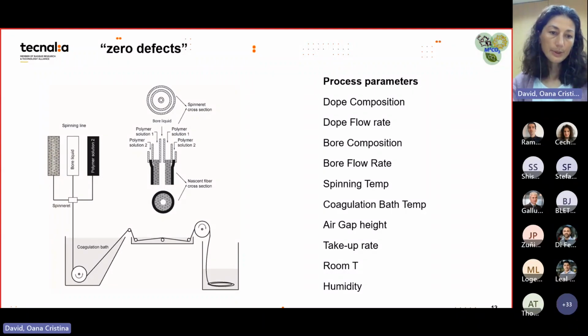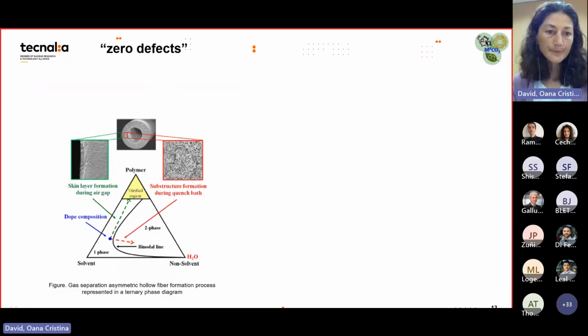So again, going back to the spinning device, as I said before, there are many process parameters we can change. The most important is the dope composition. Afterwards, when we actually do the process, we can change the dope flow rate, the bore composition, bore flow rate, the spinning temperature, coagulation bath temperature, air gap height, take-up rate, room temperature, room humidity, and even the coagulation bath liquid, which we could vary in principle. We are trying to stick to water because there are huge volumes involved.